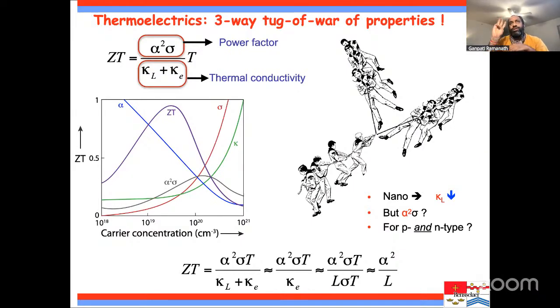And the ZT depends on three properties: alpha, sigma, and kappa. Before, there's not some kind of a Greek fraternity. Sorry, alpha is the Seebeck coefficient, sigma is electrical conductivity, and kappa is thermal conductivity. These three are unfavorably linked in nature in most materials. So when we thought about this, we found that, okay, kappa, basically you can make it as small as you want by nanostructuring, which is good.